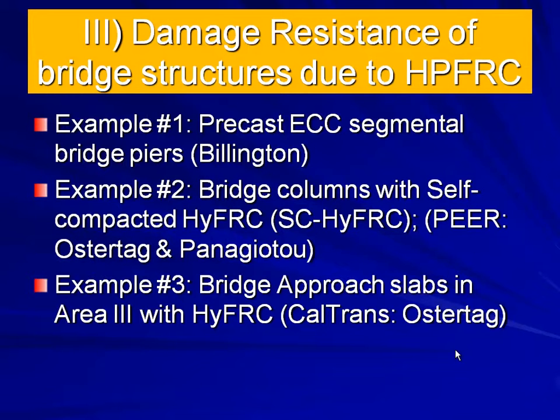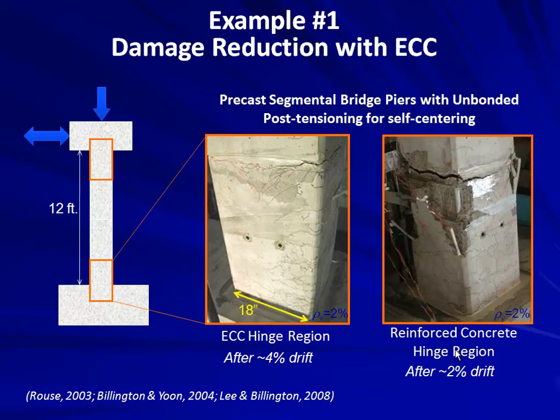Damage resistance in regards to bridge structures, I will have 3 examples here. Example 1 with ECC, and then the other examples were funded by PEER and by Caltrans, specifically in regards to the hybrid fiber reinforced composite. Example number 1 was a study undertaken by Professor Billington at Stanford, and she looked specifically into the precast segmental bridge piers, and she used the ECC in that hinge region right here. And what you can see here in regards to damage reduction, you have definitely a very large damage reduction at much higher drift ratios compared to your reinforced concrete, the conventional pier. So you really have that evidence of that damage reduction.